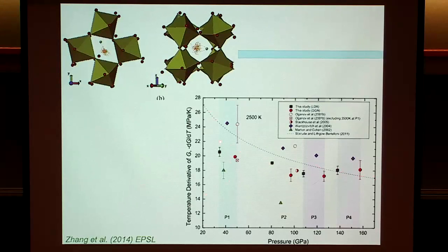Instead, the molecular dynamics simulations show a much gentler dependence of the shear modulus on temperature. And the difference here is not the ab initio theory per se, it's approximations in the statistical mechanics. This calculation assumed quasi-harmonicity. These calculations don't make that assumption. They're more expensive, they're harder, but in this case it was well worth doing. And you get a much gentler dependence, which then has implications for understanding the composition of the lower mantle.